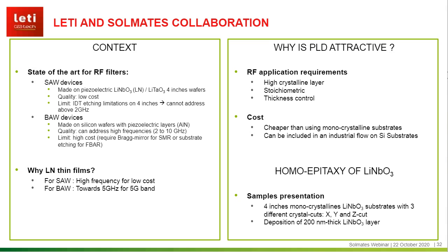The bulk acoustic wave resonators are made with piezoelectric layers such as aluminum nitride. They address high frequencies but are expensive as they require several conditions. The deposition of lithium niobate films is a new path to, in the first place, process SAW devices for low cost, and then process BAW devices with an even higher frequency of resonance.